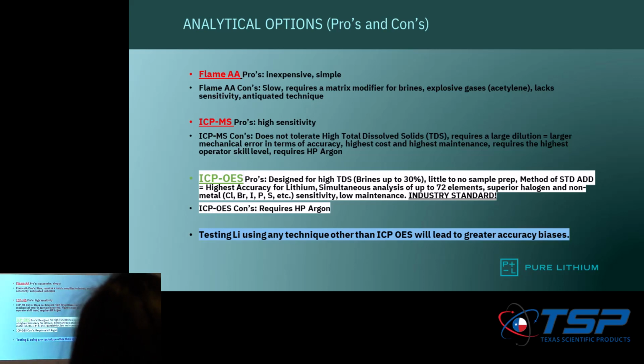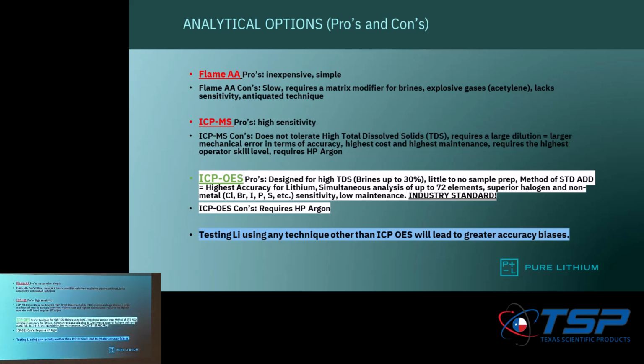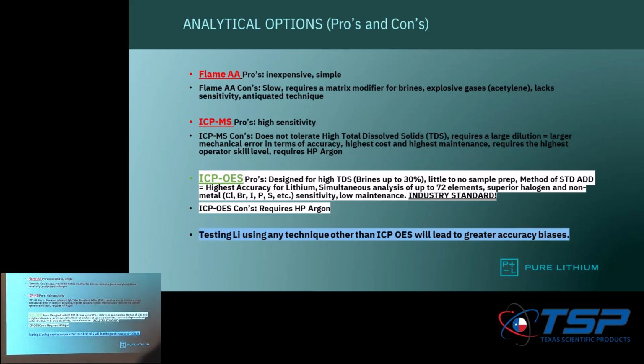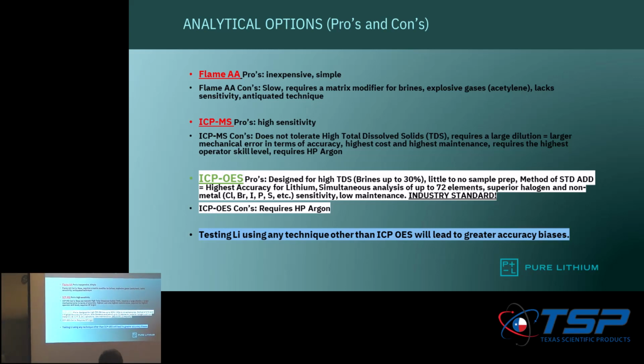ICP-MS gives you high sensitivity. Regardless of all the papers and everything, it does not tolerate total dissolved solids for a true production environment. You have a lot of maintenance, and the other problem is if you do a large serial dilution, and that's one of the biggest problems with this. People will look at a battery sample and say, oh my gosh, that sample's the size of a quarter, this is going to be a very small dilution, and then they weigh it out and they realize it's 3 milligrams. Next thing you know, you're doing a 30,000-fold dilution. And you happen to make a mistake because you went to McDonald's that day, had a little sodium on your hands, you contaminated it with 50 ppb, you're multiplying it by 30,000, and now all of a sudden your Pure Lithium has sodium in it.